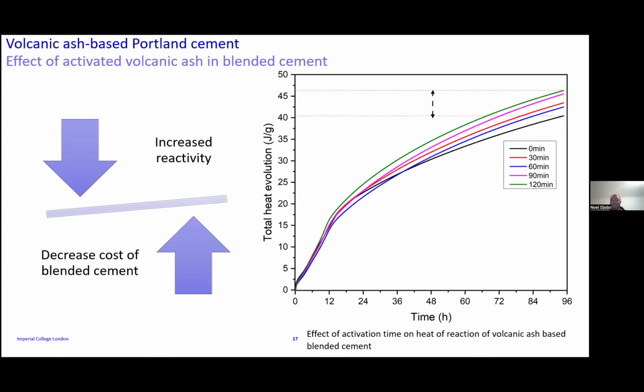since I've only added 25%, and by activating my volcanic ash I can have a more reactive volcanic ash, instead of adding 25% of volcanic ash in my blended cement, I can now add 30 or 40%. That is beneficial. First, from the environmental point of view, because we are now able to substitute Portland cement with a higher percentage. The second thing is the more you substitute Portland cement, the more durable your cement is. So when you make concrete out of this blended cement, your concrete is very durable, very good.